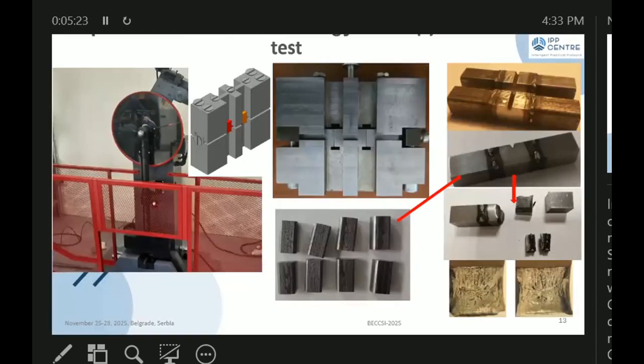Impact toughness was determined using a pendulum impact tester with a maximum impact energy of 300 joules. Given the small amount of material, a device was designed and manufactured for reconstruction of the Charpy specimens using 1 broken half and 2 side inserts. The Charpy specimens were reconstructed using laser welding. We used standard Charpy specimens with a notch dimension of 10 by 10 by 55.